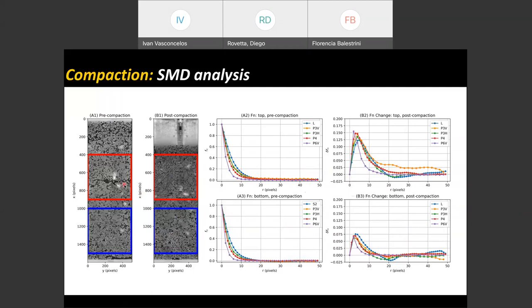This is probably due to the fact that this part of the sample has this big crack in it that you can see here that creates statistical anisotropy for this particular part of the sample. At the bottom, though, we can see that the pores also decrease, but they decrease less than they do at the top. So they're smaller than before, but they're not as small as they are at the top. More importantly, we can see a negative bump here at 20 pixels that says that even though we decreased the size of the pores, the pores have rearranged themselves, so now we have more pores at distance. So we have smaller pores, but we have more pores, and this is how we've accommodated a greater porosity. Please remember this, because we'll see this in the effective properties again in a minute. So, noticeable changes in volume fraction and geometry.